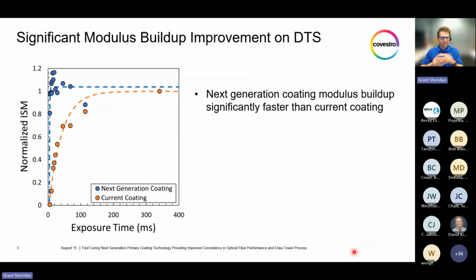So in addition to the cure speed, we also feel that the mechanical property buildup is just as important, if not possibly more important, to ensure that we're protecting the glass itself. Because if you cure your system but you have no mechanical properties, then the primary coating isn't really doing a whole lot. So shown here, we have the normalized in situ modulus, normalized to the maximum in situ modulus we see at the largest exposure time, versus exposure time. And once again, we can see that the next generation coating is significantly faster at building up the modulus, building up the mechanical properties, compared to the current coating technology.